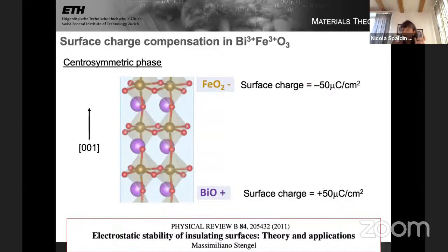The fact that the internal polarization cancels with the spontaneous polarization also has profound implications for the surface chemistry, though, because it means that the surface charge compensates. So if we look at the surface charge in the centrosymmetric phase, the FeO2 minus surface in the 001 direction turns out to have a surface charge of minus 50 microcoulombs per square centimeter, and the bismuth oxygen plus surface has a charge of plus 50 microcoulombs per square centimeter.